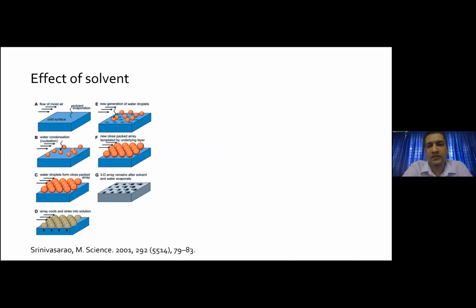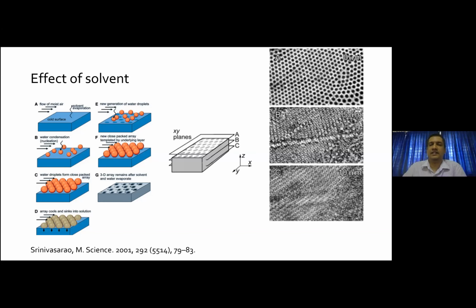If the solvent molecule is lower in density compared to the condensate, the water droplet, then you always end up with a single layer of this condensate. And this work has been thoroughly examined with various solvents by Professor Srinivasarao, where he proved that by using carbon disulfide and toluene, you can get two different patterns, and also the depth profiles vary.